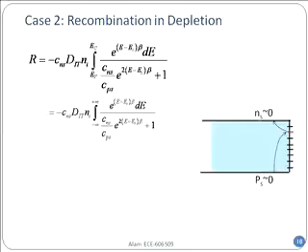So in order to do this integral, I need to take the limit to plus minus infinity, EC and EV to plus minus infinity. I can do that because most important traps are always in the middle region, right? In the middle region. So conduction and valence band are many kT away, because 1 eV, even if it is like 10 kT away, for the exponential, it looks like infinity. So therefore, I substitute with plus minus infinity so that I can do the integral easily.